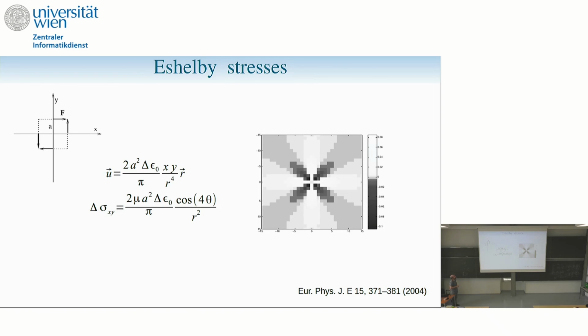But okay, I'm sorry, this is not the best picture I have. I could have found something. Essentially, the point is that the shear stress associated with this has a quadrupole form, so it's cos 4 theta. What it means is that if I have a shear here, I will increase the shear stress along the horizontal and the vertical line, and reduce the shear stress along the diagonals. And so that's why you have this cos 4 theta.